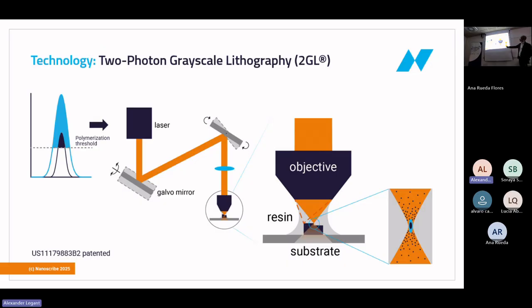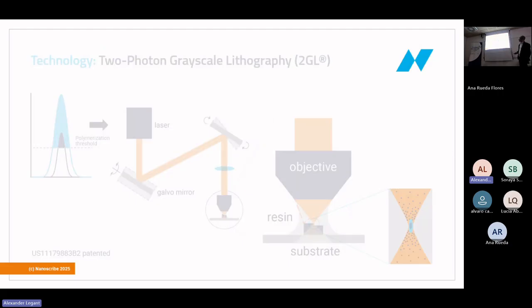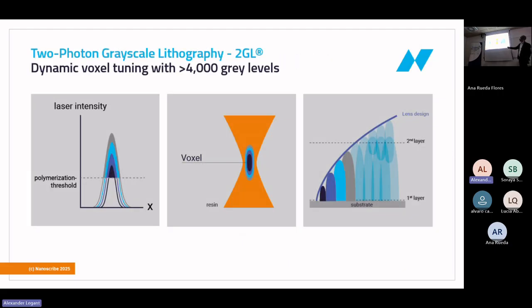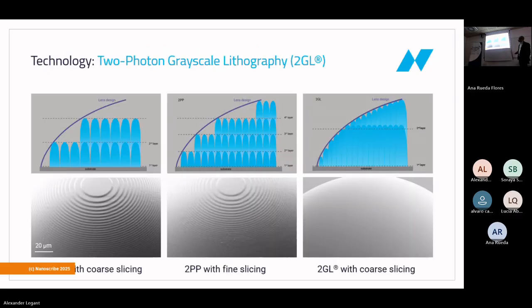Now, by increasing or decreasing the laser power, we can increase and decrease the voxel size. What you see here again with some more examples, and if at the same time you scan along one line, you can very nicely follow such a trajectory, such a curve, for smooth surface roughness of microlenses, or for example, the side of microfluidic channels.